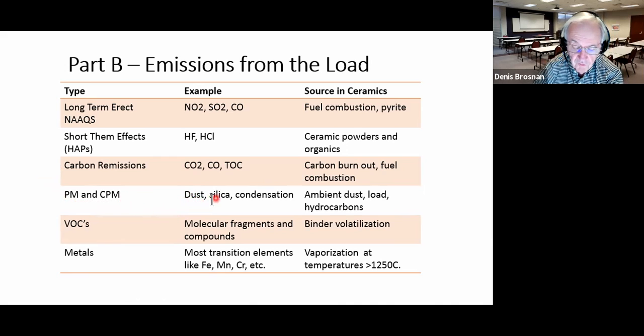So particulate matter comes from dust or silica, anything that is in the plant environment that's taken through the combustion system, because as you know, some dust is going to make it into the burners. It's from dust that's coming down the tunnel with the excess air in the tunnel. If it's a tunnel kiln, it's dust shaking off the product. It's condensable particulate matter from whatever's happening within the kiln. We have volatile organic compounds, and those can be molecular fragments and compounds that evaporate. And then metals, species that are emitted from the kiln as metals. And those include things like iron and manganese and chromium, which can be important in ceramic manufacturing.